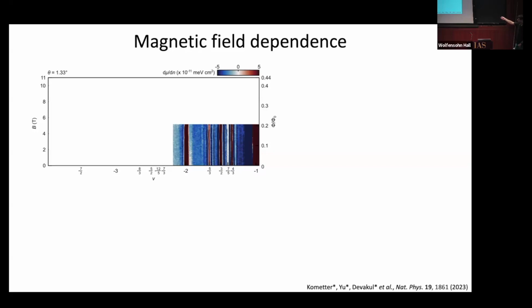I want you to focus first on this regime where we have relatively low magnetic field and relatively low doping, up to 2 holes per Moiré unit cell here. This is 1 hole per Moiré unit cell. You can pick out several vertical features appearing here. There are incompressible states, like a Mott insulator, when you've filled this with 1 hole per Moiré unit cell. There is a band gap also when you fill 2 holes per Moiré unit cell. And you can see that there are other incompressible states at rational fractional fillings. These correspond to the generalized Wigner crystals that I was showing you before. So this is very similar to what had been seen previously in past measurements of transition metal dichalcogenides.